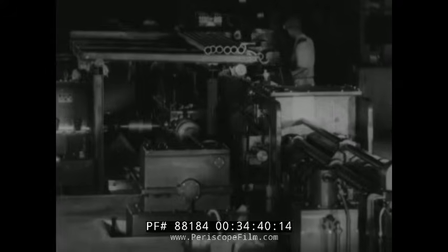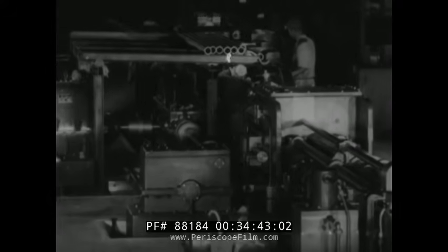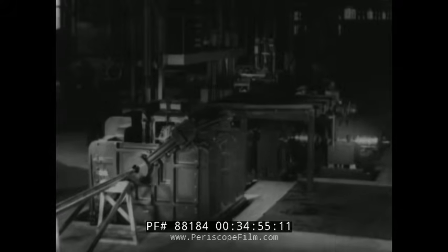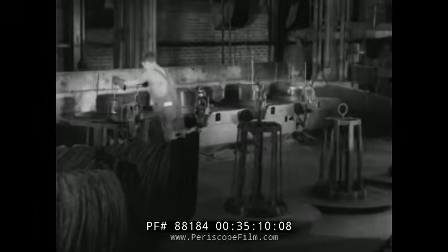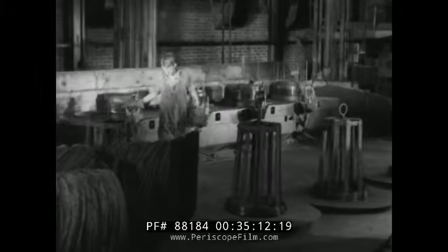On this tube reducing machine, very heavy reductions are possible and exceptionally long tube lengths can be produced. The tube is reduced over a tapered mandrel by means of a specially designed die. Flat bars are sometimes cold drawn to meet unusual specifications. Some heavy wire is produced which is drawn from individual coils on this 4-reel bench.